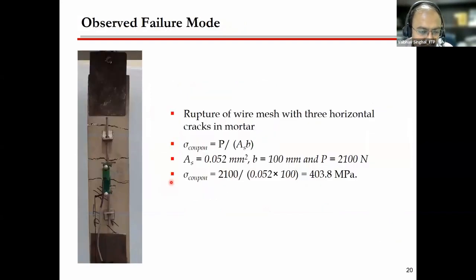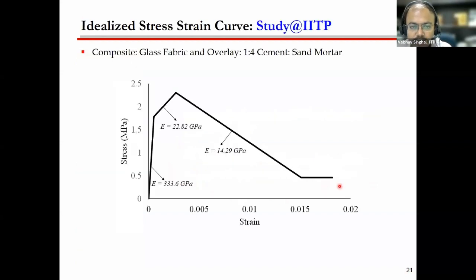Now this is the failure which we have seen when we did the testing at IIT Patna. You can see the multiple cracks in the coupon, in the specimen, and using the peak load you can find out the ultimate strength of the reinforced cementitious matrix. Here we have used the steel wire mesh, and the strength came out to be nearly the yield strength of the wire mesh, which is about 403 MPa.